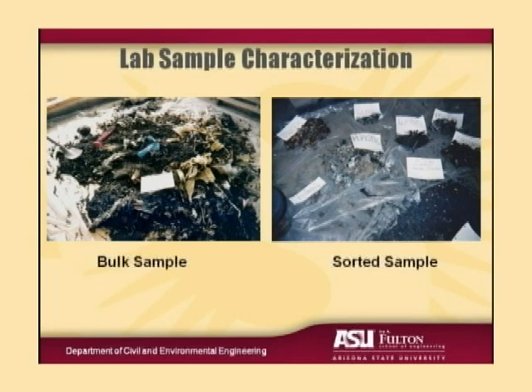And I think at OII, the average amount of soil and soil-like material was on the order of 80% by weight, less by volume, of course. And we had some samples that were as much as 99% soil and degraded waste material, coming down from the wet end of the landfill and representing a very high state of degradation. And that had an impact on the properties, as I'll show you in a minute.